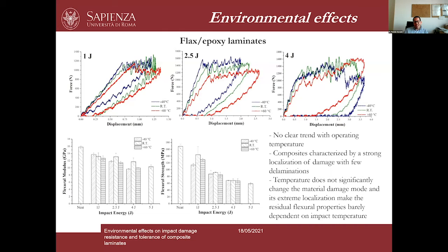This is probably related to the fact, as we have seen, that these composite materials are characterized by a strong localization of the damage. Basically, in these composite materials, the delaminations are really limited compared to standard and conventional composite materials. So it is expected, especially due to this strong localization in the presence of the cross-shaped micro cracks, that the temperature is not able to change the failure mode. That's why we didn't detect a significant effect of the temperature on the residual properties. But by the way, the temperature had a significant effect, for example, on the energy absorption ability of these composite materials.